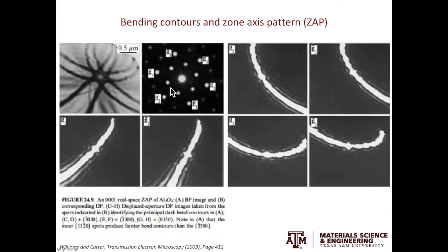This is a really nice example to show you the relationship of bending contour to the g-vector you use. Each bending contour corresponds to one g-vector. Because the excitation error at that specific g-vector is equal to zero, you see the presence of the bending contour. When you change the g-vector, different sets of bending contours will show up.